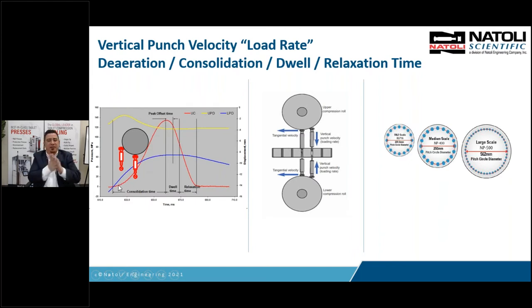So let me say this. If you've got a tablet press with a very large roll and you're running with the head flat, say 9.5 millimeter, running at a constant velocity. Now you're running another press with a small roller, the same turret velocity with the same head flat, 9.5. Well, you're going to get the same dwell time for these different presses because the head flat's 9.5 millimeter. It hits the roll, comes down, it rises 9.5 millimeter, no matter how big or small the roll is. But the press with the larger roller is going to have more consolidation time, which is more time to get the powder consolidated and get the air out and get the particles touching each other. So the roll size is very important.